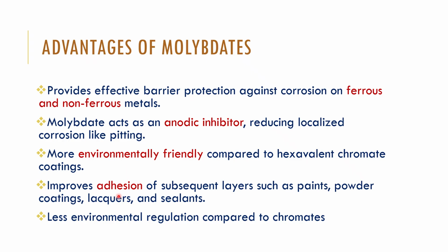It improves adhesion of the subsequent layer. If you want to apply a paint over a surface where paint should be 100% adhered to the surface, first give this molybdate coating. So it forms micro cracks, means it is a rough surface. Over that, if you apply paint, it gives a very good adherent coating, and this paint lasts for very long time. Molybdate coating also protects from corrosion. So double layer protection you get. Or apply a sealant, apply lacquer over the surface, anything you can do. There are many processes to be carried out, any method you can use. Less environmental regulation compared to chromate because it is an environmentally friendly process.